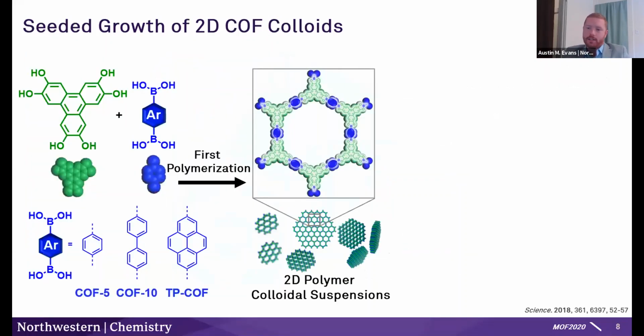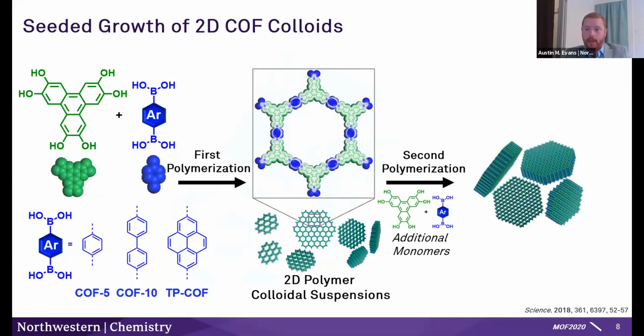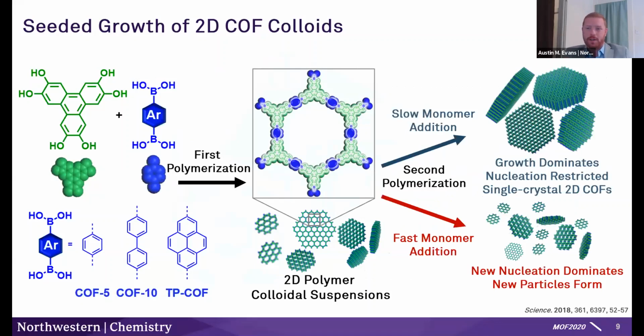And this inspired us to think, well, is this because we've gotten away from the kinetic trap of aggregation? Now can we grow these crystallites further? We thought one simple way to do that might just be to introduce more monomer. From our earliest experiments, we started to infer that perhaps we would need to choose one type of regime where we could either favor nucleation or growth, because there's nothing stopping new species from being nucleated. I'm going to gloss over a lot of the technical details here so I can get to the more application-relevant studies. But I think the ability to selectively tune which process is operative is key here.